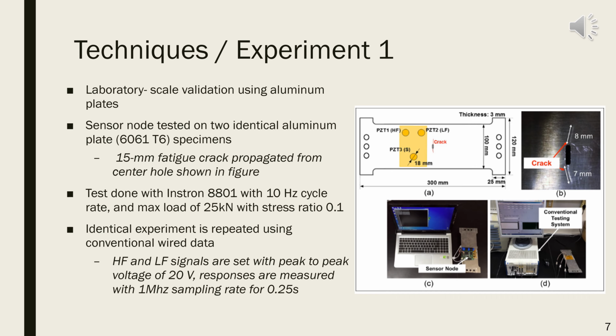The laboratory scale validation was using aluminum plates. The sensor node was tested on 2 identical aluminum plates of 6061 T6 specimens. Each had a 15 millimeter fatigue crack that was propagated from the center hole shown in the figure on the right. The test was done with an Instron 8801 with a 10 Hz cycle rate and a max load of 25 kilonewtons with a stress ratio of 0.1 applied to both of these aluminum plates.